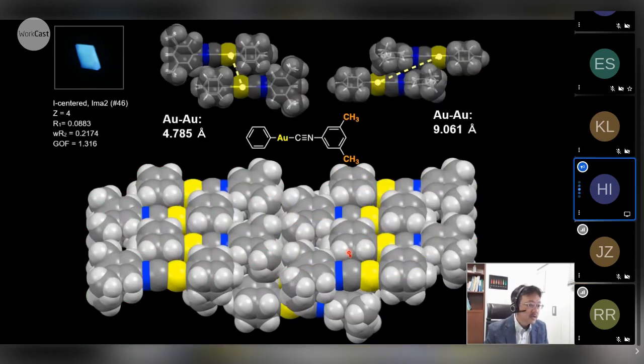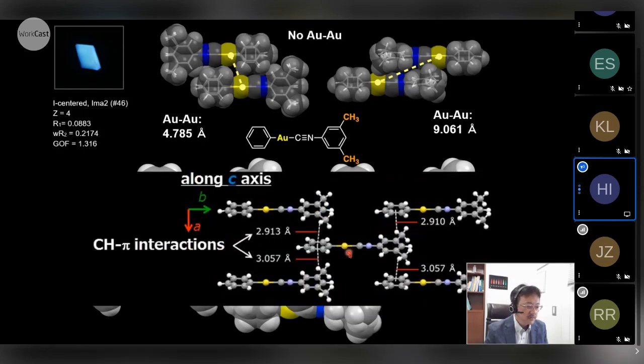And interestingly, there are no aurophilic interactions anymore. Instead of the aurophilic interaction, you can find the CH-pi interaction. Maybe aurophilic interaction gives some enthalpic stability, but this CH-pi interaction would compensate for the loss of enthalpy stabilization that came from the aurophilic interactions.